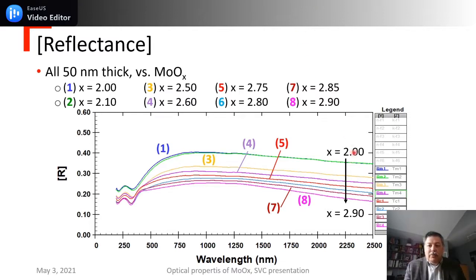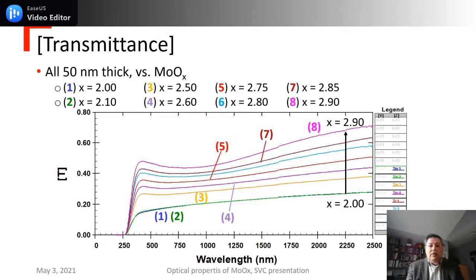From stoichiometry of 2.0 to 2.9, the reflectance becomes smaller, and we should know that that will mean that the refractive index will be smaller. So the higher the refractive index, the greater the reflectance. This is the transmission of the same samples. As the stoichiometry, as the oxygen increases from 2.0 to 2.9, the transmission increases. This will mean that the K, the extinction coefficient, is decreasing as we add more oxygen to our samples.